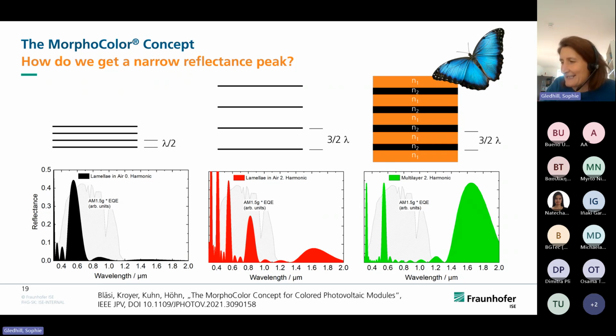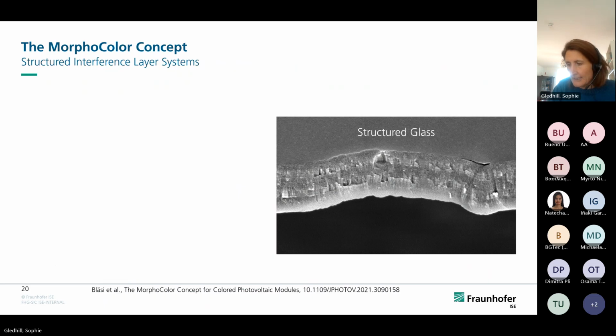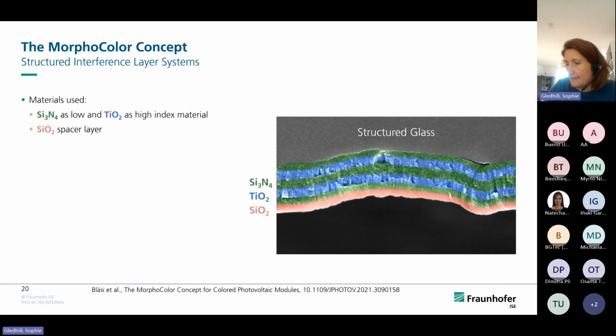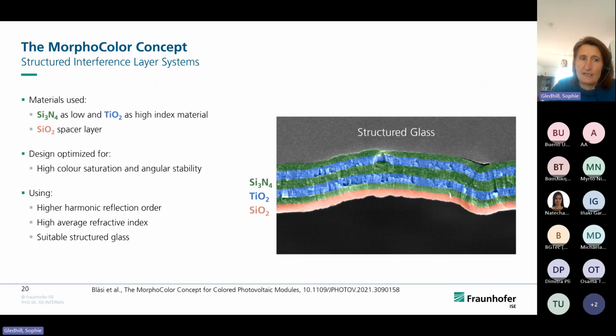Now, lamella suspended in air are, of course, not a realistic structure for use in a PV system. As the Morpho structure shall be integrated at the interface between our cover glass and encapsulant, more materials and more interfaces must be considered for an accurate modeling. And the thin film system that we actually use consists of high refractive index layers and low refractive index layers stacked up. So our real system is composed of a thin film sputtered silicon nitride as the low refractive index material and titanium oxide as the high refractive index. The design is meant for high color saturation and angular stability. And we get the good coloring because we're using this higher harmonic reflection order, we have a higher average refractive index, and we have a suitable structured glass.